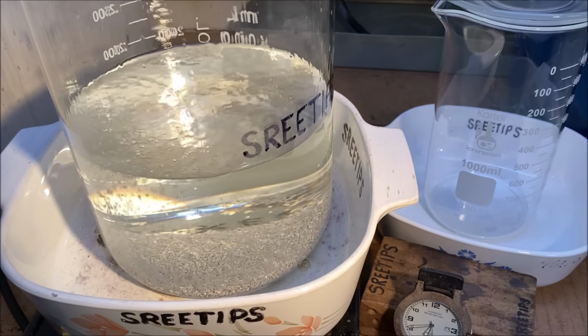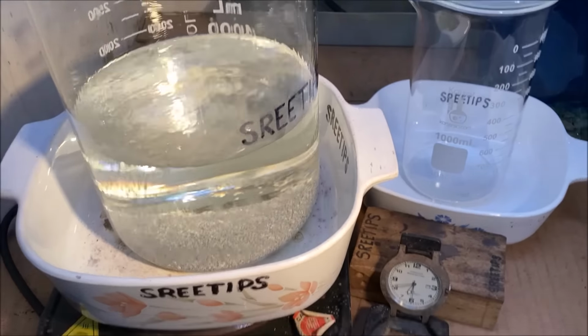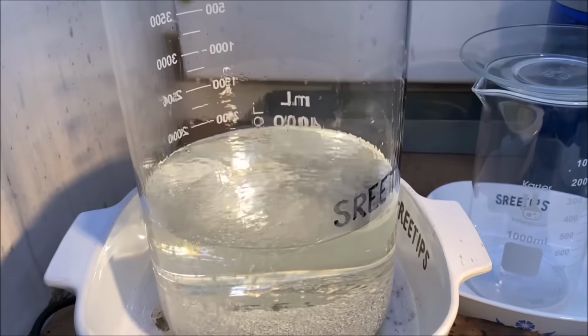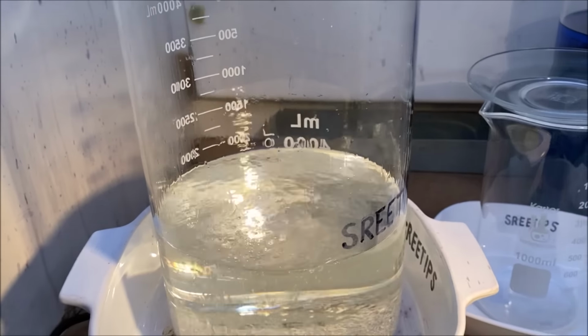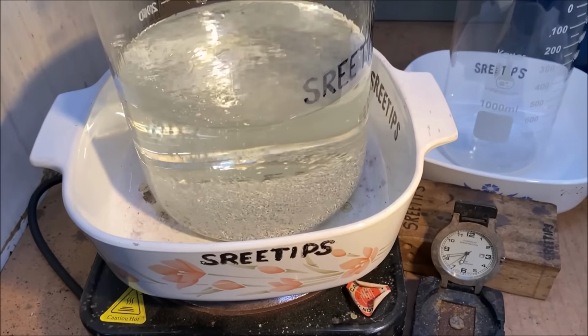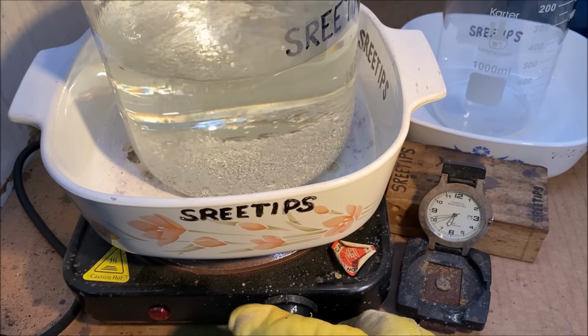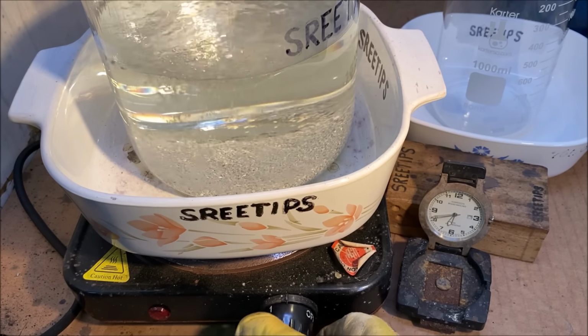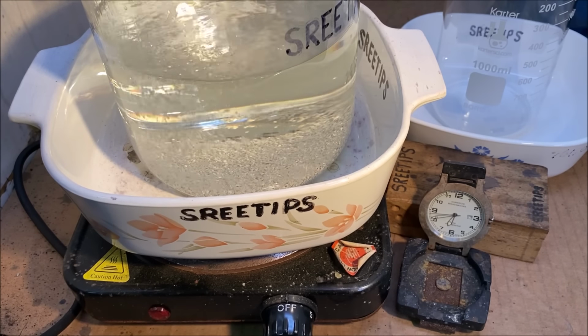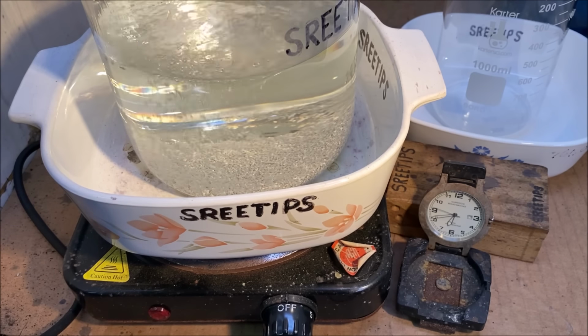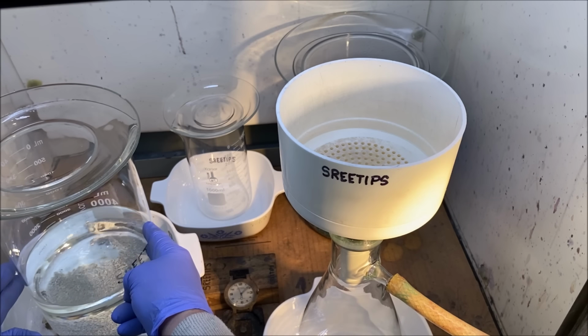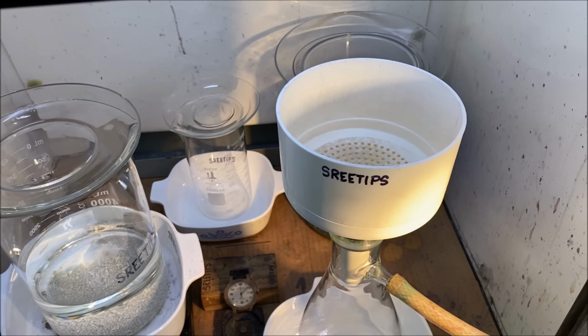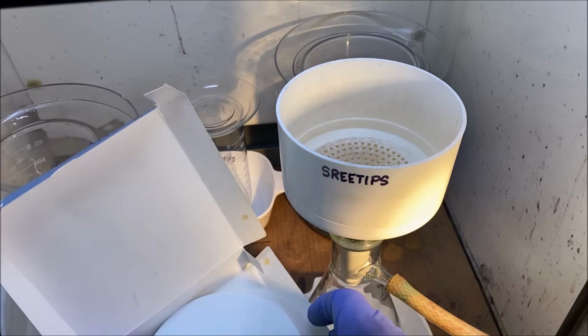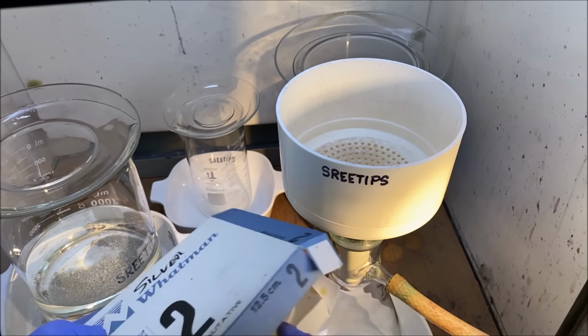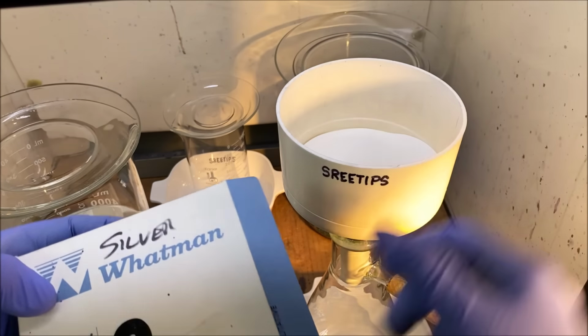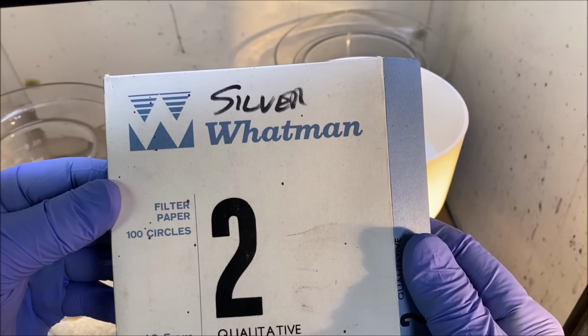Okay, we've got the electrolyte completed. All the fumes inside there are gone, which tells me that all the nitric acid has been consumed during the reaction, and that's important so that we don't throw out fumes as we operate the cell. So I'm going to turn this off and let it cool down. I've allowed the electrolyte to cool completely. Now we're going to set up a filter here and filter the solution.